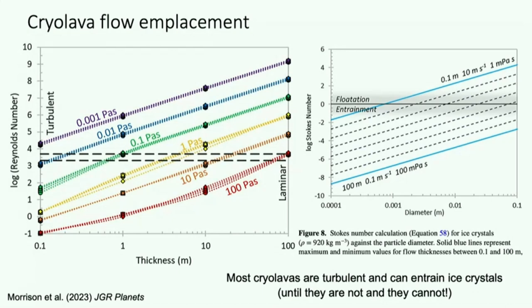All right. So on the left, this is actually log of the Reynolds number versus the lava flow thickness, but what this tells us basically is, are we looking at turbulent or laminar flow? So most cryolavas are going to be turbulent when they erupt, because they're going to have viscosities that are fairly low, right? Especially if they've got no crystals in them, they're likely to be in this range. And so whatever their thickness, and yeah, this seems like a ridiculously large range of thickness, but does anybody know how thick a cryolava flow would be at the vent? So we kind of picked what we think is probably in this range, but just to cover our bases, we went an order of magnitude lower and higher than we thought was probably reasonable.